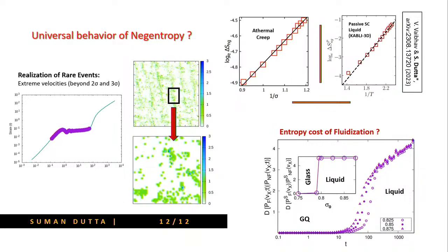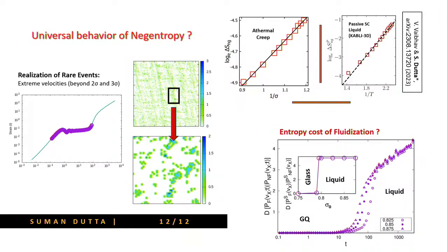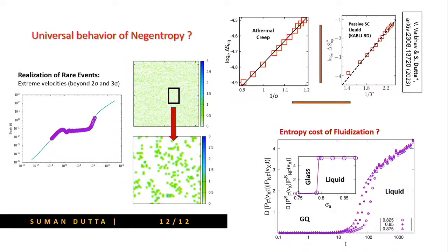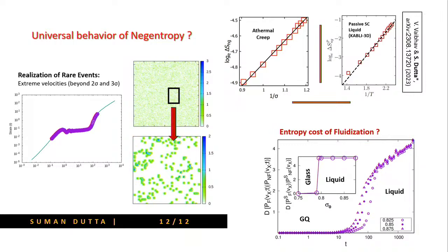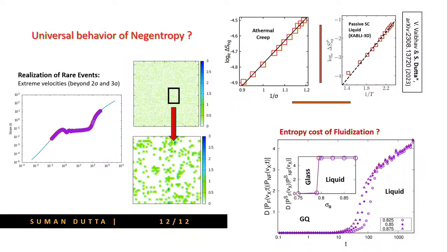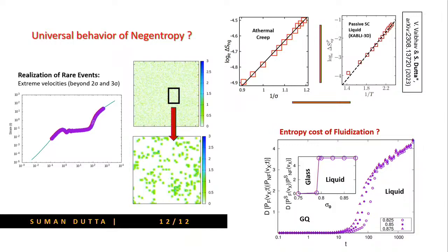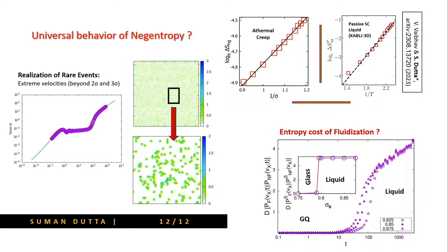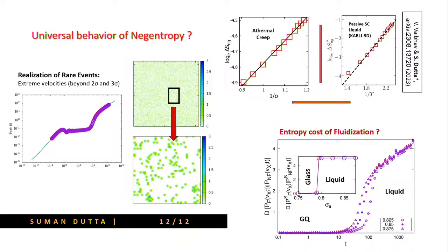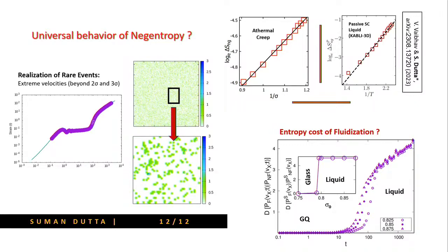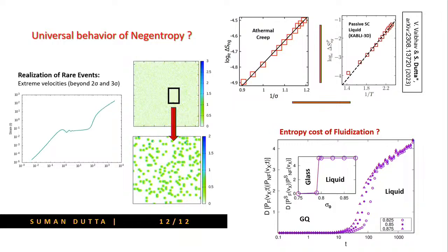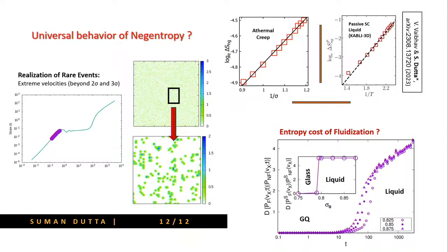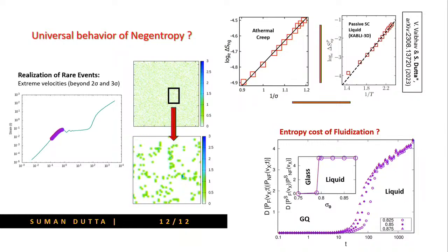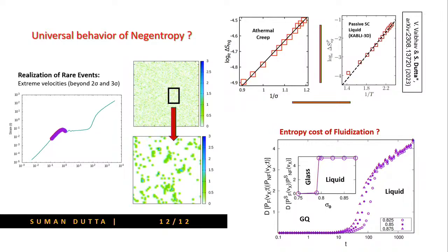To understand those rare events, because I said these plastic events are very stochastic in nature, and also, as I said, their spatial accumulation finally leads to the failure. That could be understood using this investigation, where we are showing that these extreme velocities or extreme displacements, which are beyond 2 sigma and 3 sigma, are responsible for this kind of failure. This failure leads to this drastic change, and this disorder in the system is making the system